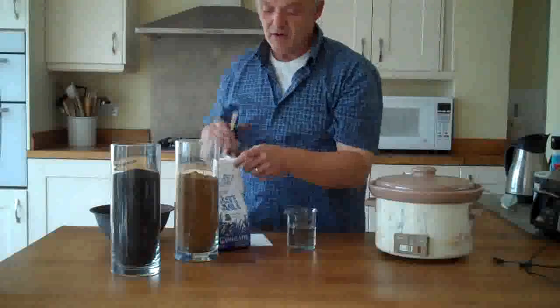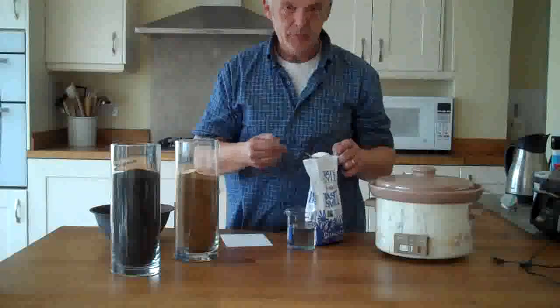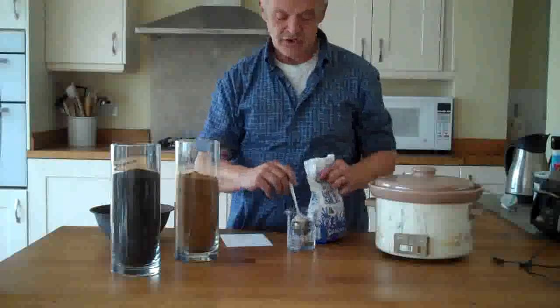The amount of graphene coating you give to the sand is going to depend on the amount of sugar that you put into the water. You can change that and play around with it until you get a carbon loading that you're quite happy with. You can do a whole series of little experiments where you do 100 grams of each, progressively increasing the carbon loading until you get one that has a good result. Most of them have a fairly reasonable result, but if you want to fine-tune it, measure and weigh your volume of water and sugar and just add it.